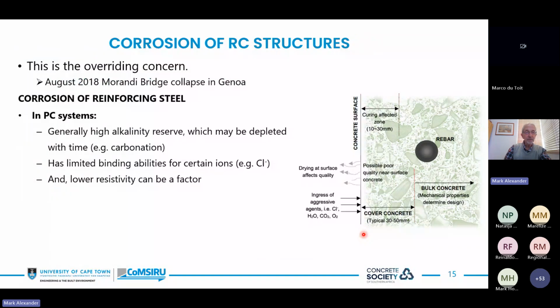And in PC systems, with regard to corrosion, generally, this is again why plain Portland cement systems have done so well, because we've got this high alkalinity reserve, which admittedly can be depleted. We have, on the other hand, limited binding abilities for particularly chlorides, and it has a low resistivity, but in general, it does quite well.